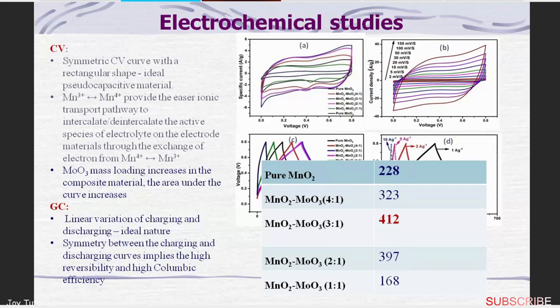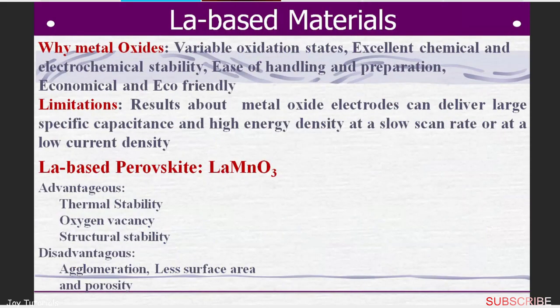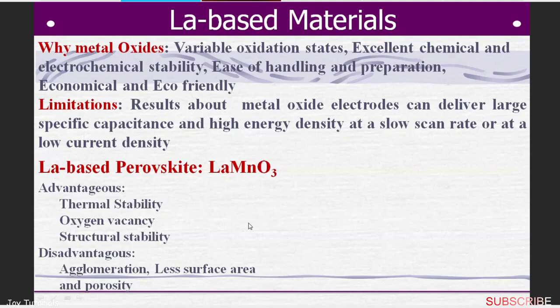When you go for a higher scan rate, it is difficult to maintain the specific capacitance. That means you have to apply more voltage with respect to time, and this can cause loss of specific capacitance in a faster way, so it is not much useful. When subjected to higher scan rate, it should still be stable. So we look for a lanthanum-based perovskite material. Perovskite material has an ABO3 structure, where A is lanthanum-based and B is a transition metal — so they form ABO3, like LaMnO3.